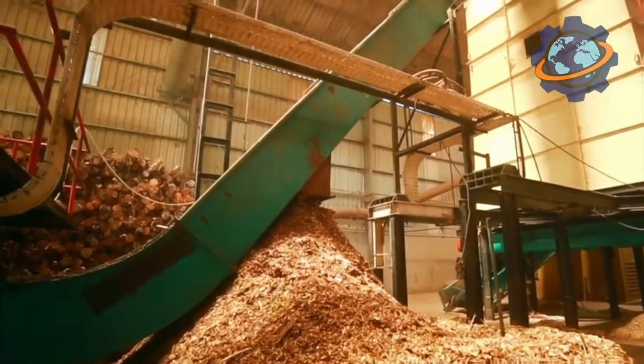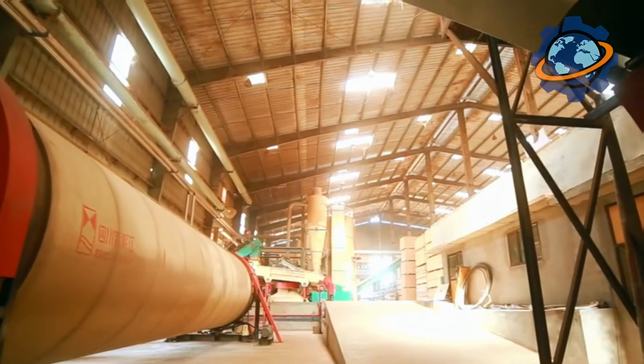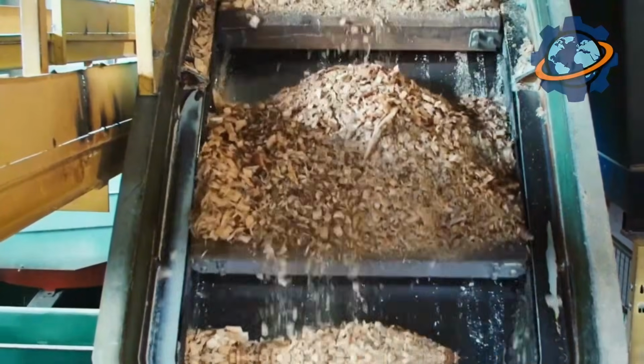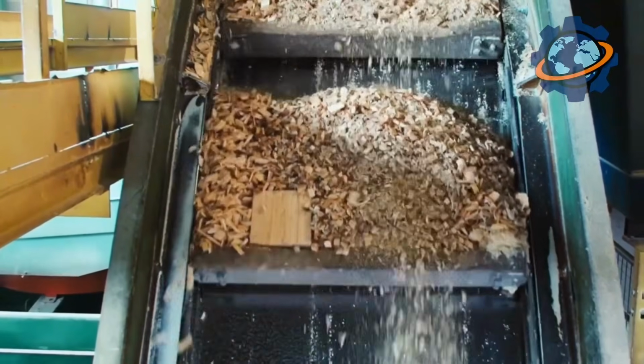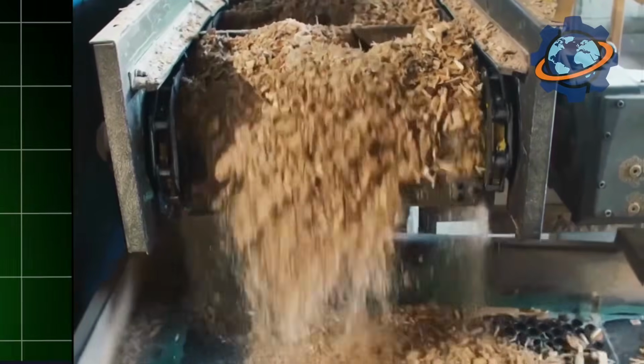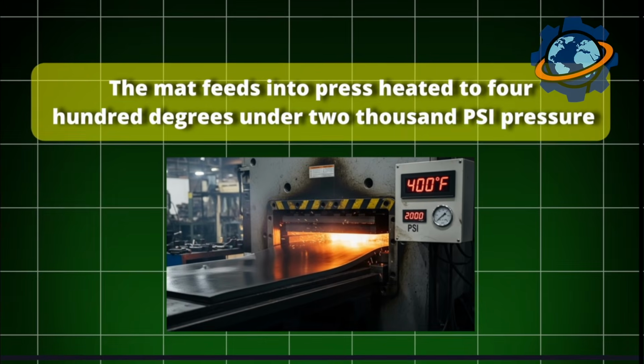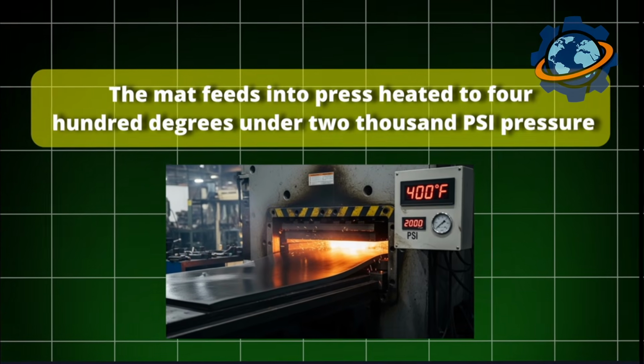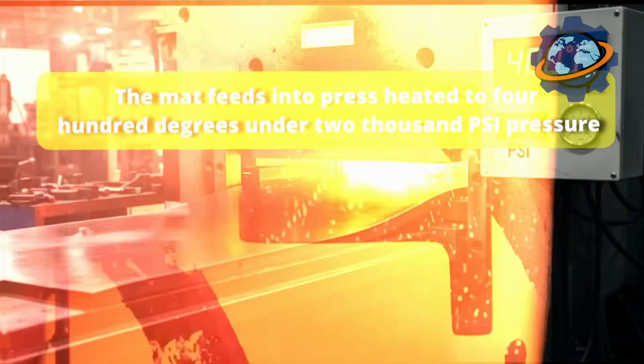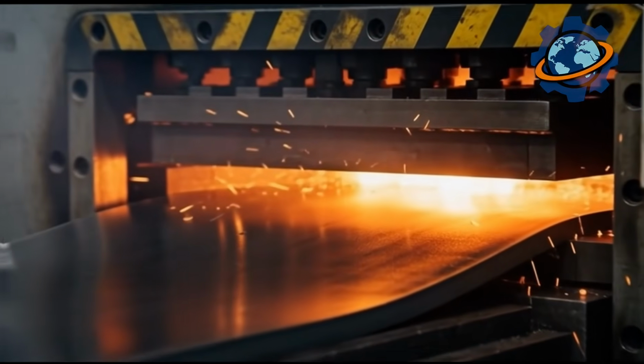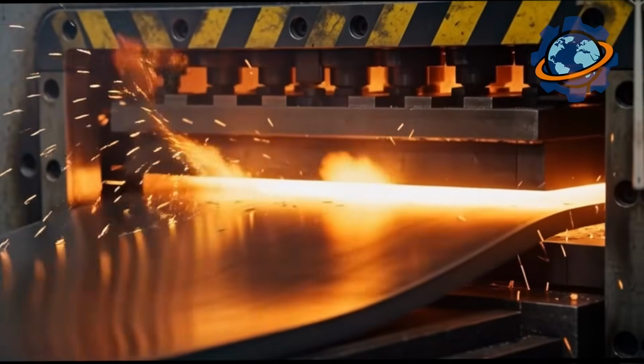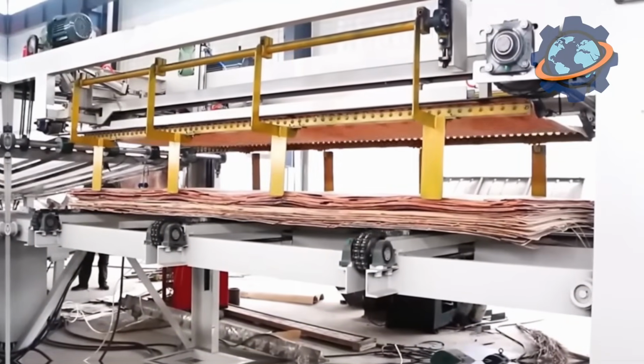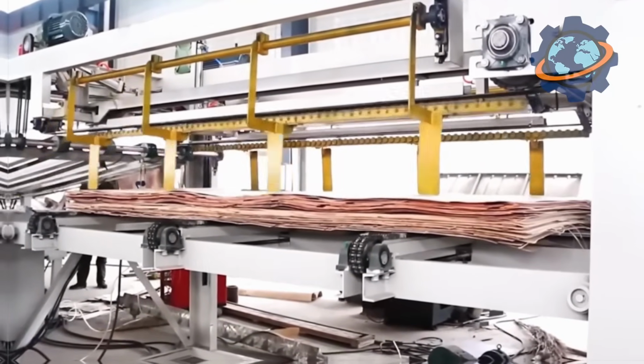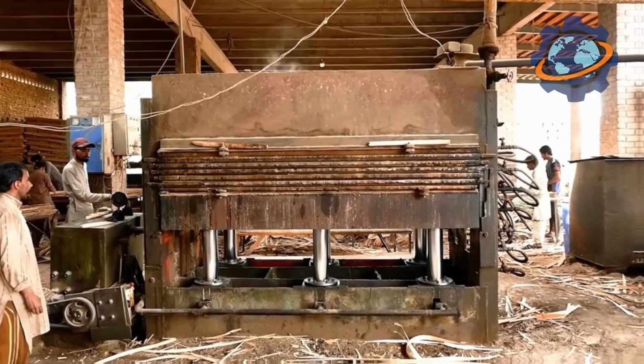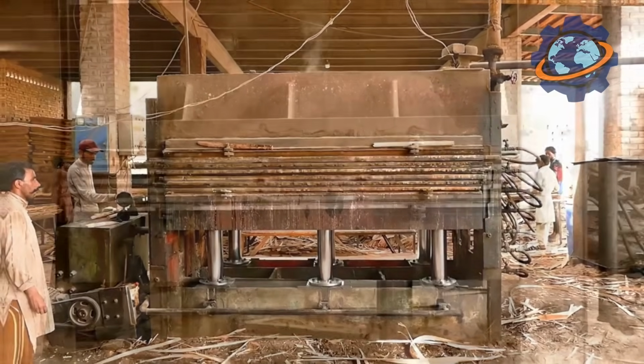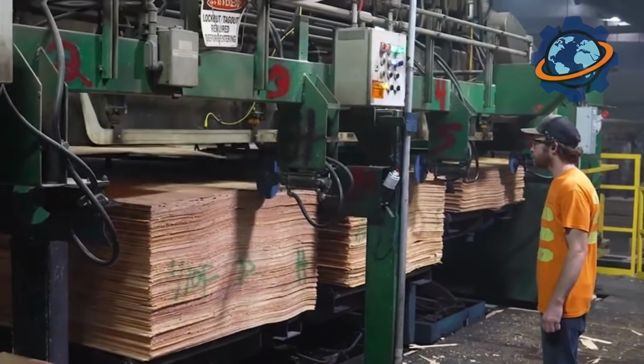The mat, a loose collection of oriented strands 8 inches thick, enters a continuous press. Unlike plywood's batch press, OSB uses a continuous process. The mat feeds into a press heated to 400 degrees under 2,000 psi pressure. As it travels through, thickness compresses from 8 inches to 7/16 inch while the resin cures. The panel exits as a continuous ribbon, cut to length by flying saws. Production speed reaches 600 feet per minute, 1 4x8 panel every 0.8 seconds.